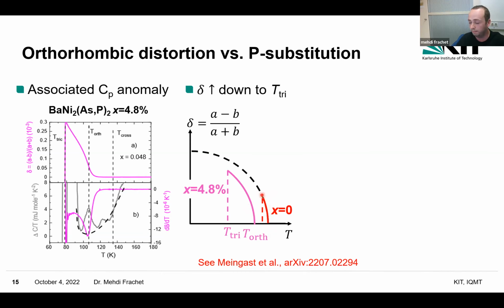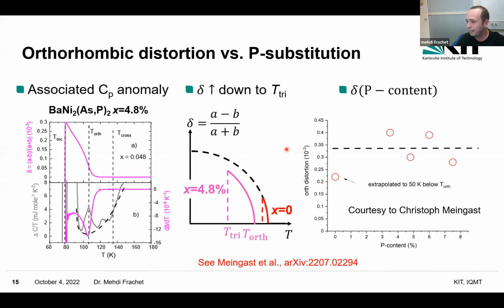Okay, so it makes things a bit complicated to compare, and that's why this orthorhombic distortion looks very small in the undoped compound. So Christoph Meingast sent me this nice plot actually, of the orthorhombic distortion as a function of phosphorus content. And what he did is just to extrapolate this orthorhombic distortion to lower temperature in the undoped compound as if there was no triclinic transition. And what you can see is that it suggests that the amplitude of the orthorhombic distortion is not that doping dependent. It seems to be rather constant as a function of doping.